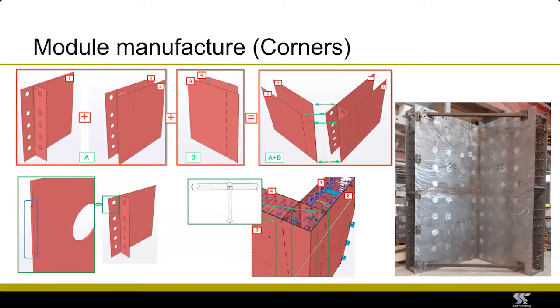When we come to corner modules or modules that have internal walls as part of them, the process starts in exactly the same way, but in addition, we have now corners that we need to weld, which we don't have direct access to. So instead, these are welded from the outside using intermittent welds. So we cut slots into the outer plate and a sawtooth into the inner plate that fits into these slots, and then the welding is completed from the outside. And that, of course, has to be structurally verified that the intermittent weld is adequate for the corner.